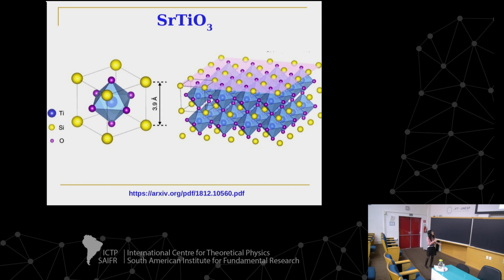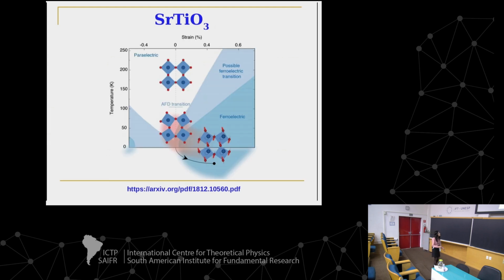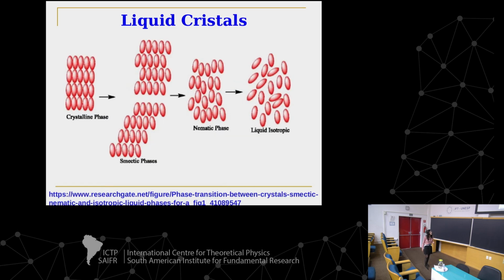And if you want to play games and put pressure, for instance, in the diagonal, you actually change the structures that you end up with, because it's like you are pressing some of the oxygens while they are dancing, doing this circular movement. So again, this is a very fascinating material, as many materials, that changes structure with temperature change. Here I'm just drawing the oxygens, how these things are changing. And I didn't put it, but this is the pressure. As you change pressure, you change this rotation that was more in one way to another way, which makes certain properties vary a lot. So it's not just a beautiful change of structure, it means the material can become ferroelectric, have different types of properties that are very fundamental.